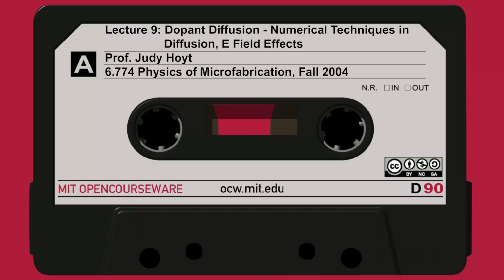The boron basically gets pulled in underneath the source and drains, and there's quite a bit of loss of boron from the channel region into the source drains. That is due to the electric field effect, which is not predicted on the left-hand side. So even though the h factor, the enhancement in the arsenic diffusivity, is limited to at most a factor of 2, so there's not too much effect on the junction of the arsenic, you can see the black junctions, those regions don't change that significantly, but it dominates the diffusion of the boron underneath, at a lower concentration.